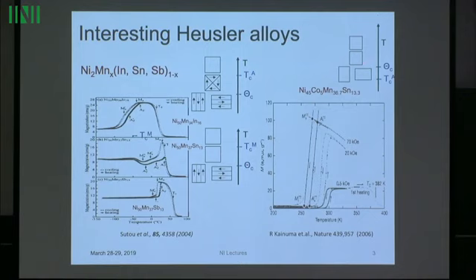So the first order phase transformation temperature can be changed by applying a magnetic field. Mathematically, you have this multi-well structure. In the models I presented yesterday, the applied field supplies an energy minus h dot m integrated over omega. H is the applied field, so of course that's a linear function of m. That tips the energy up and down, and you can bias towards one of the wells. So if it's biased like this, it's no longer at the transformation temperature, and with the bias you now change the temperature. Of course, the wells go up and down with temperature too. So now we have this new transformation temperature here. It's a very geometrical way of thinking.